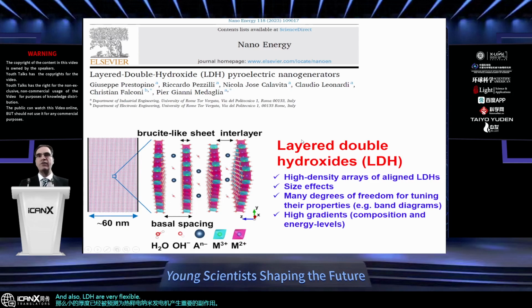There are many degrees of freedom for tuning their properties, because one can choose different M2+ in this label at the bottom, so different bivalent cations, or different metals, different trivalent cations, different anions, and also different levels of hydration, and also different ratios between the divalent and the trivalent cations. So it really is a material which offers lots of flexibility and possibility to design. Besides that, it's also very simple to grow with wet chemical methods on just aluminum substrates.